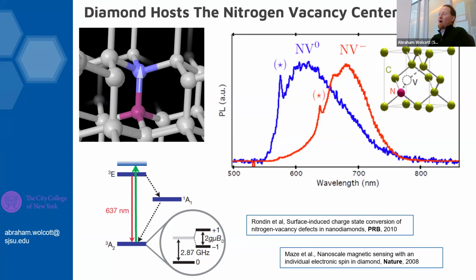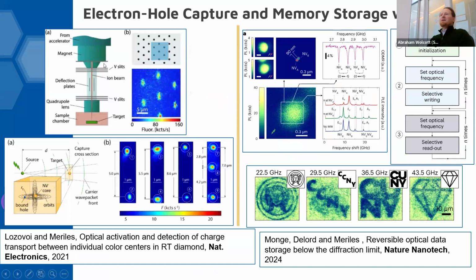And of course, for quantum dots, which I spent many years researching, the surface was always important because we had a delocalized wave function which would interact with the surface. And so everybody knew that the photoluminescence properties and the charge transport properties were tied to surface dangling bonds and defects.